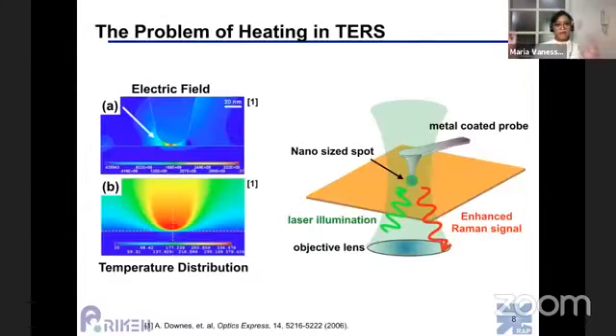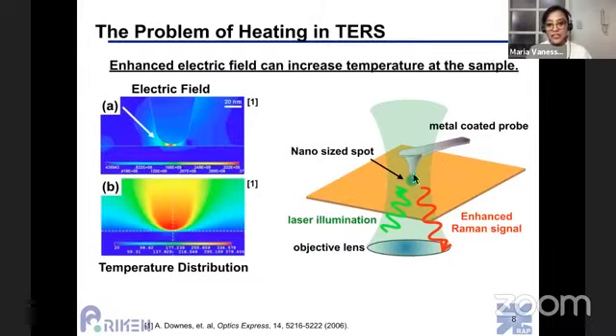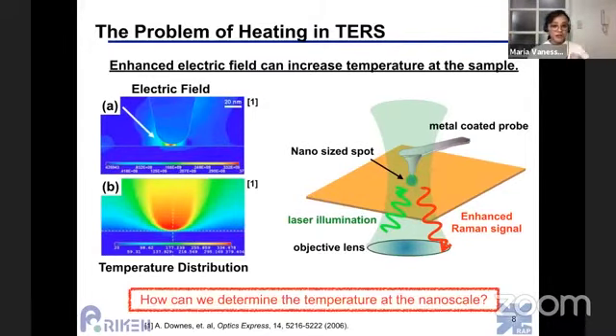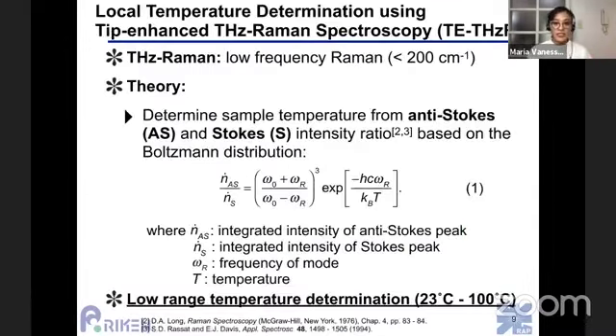Now, the research which I tackled is mainly about the problem of heating because of the enhanced electric field that is generated at the tip end. And how can we extract this nanoscale or nano volume temperature and use it for practical purposes? Now, low frequency Raman is useful for temperature determination because you can actually calculate the temperature based on the Boltzmann distribution and also the intensity ratio of both the anti-Stokes and the Stokes Raman. And by doing it via experiment, obtaining the anti-Stokes and the Stokes intensities and then crunching out the numbers based on this equation, you can actually calculate the temperature at the tip end, which is more or less the temperature at the tip, at the sample.